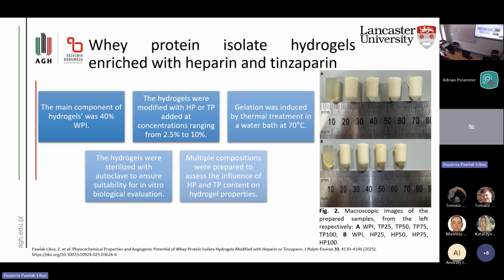And on the right, those are the samples. From the left, it's pure WPI, and then 2.5, 5, 7.5, and 10% of additive. Above is tinzaparin, and our picture shows heparin. Our hydrogels were then sterilized with autoclave, which ensures that they are suitable for in vitro biological evaluation, but it is also very important that our biomaterial can be sterilized without losing its properties, so it can be translated to clinical applications. And we made multiple compositions to assess the influence of additive content on hydrogel properties.